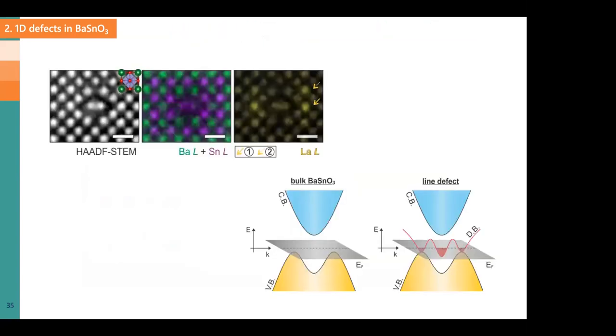And that's what we did. I'm summarizing a little where we are up to this point. We know the structure. We know this defect should create bands in a previously non-available region of the band structure. That's going to be partially filled because the electron goes and gets sucked into this defect. So these red bands I plotted here on the side, that's where it's going to go. So now the question is whether we can detect these red bands.